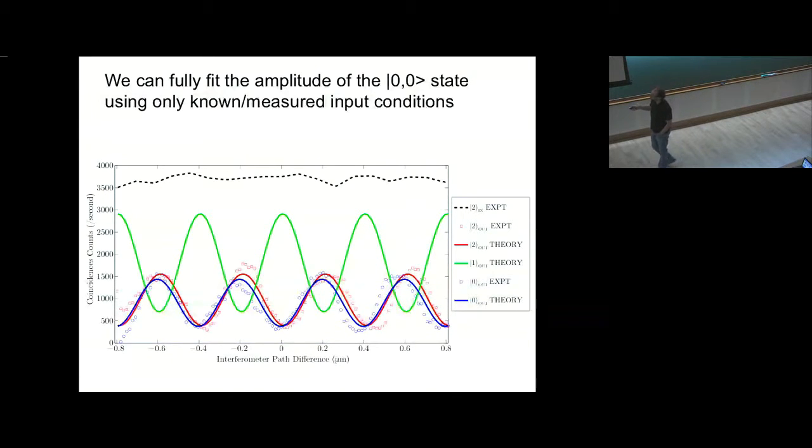But in essence, the theoretical maximum is 25%, and here we're measuring something of the order of 23, 24%. So the metamaterial is really close to ideal. The only way you can measure the complete absence of 2 photons is by making sure that you've measured everything else very precisely.